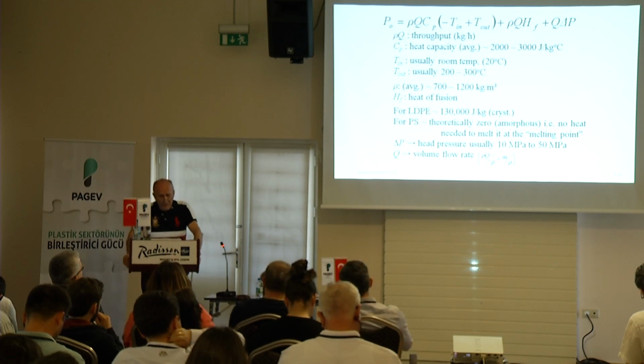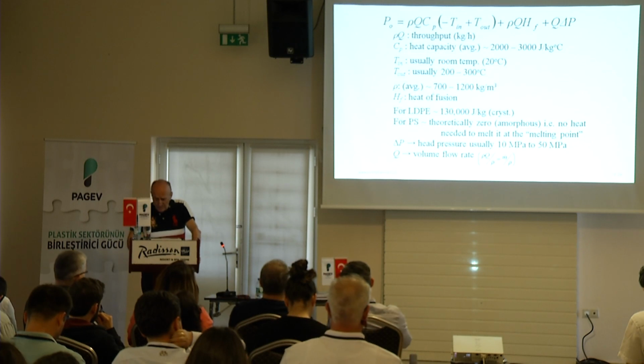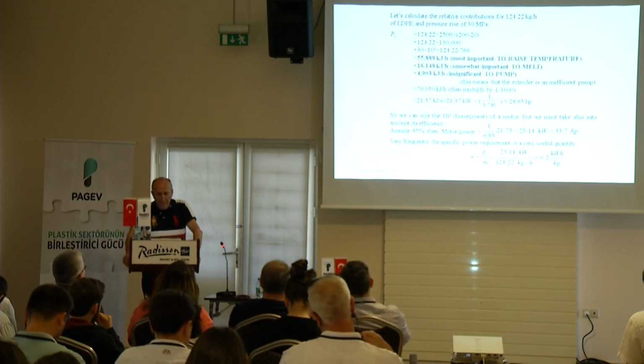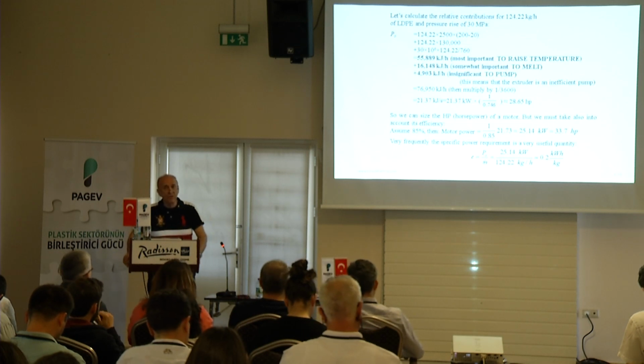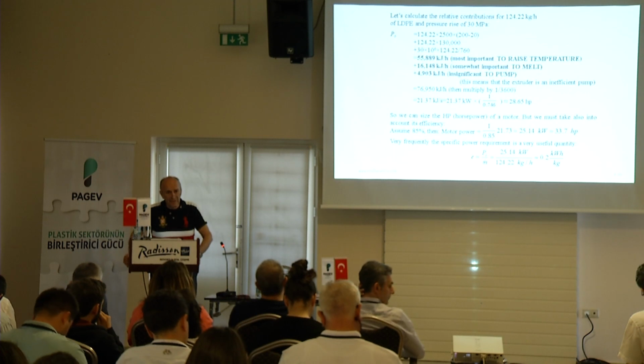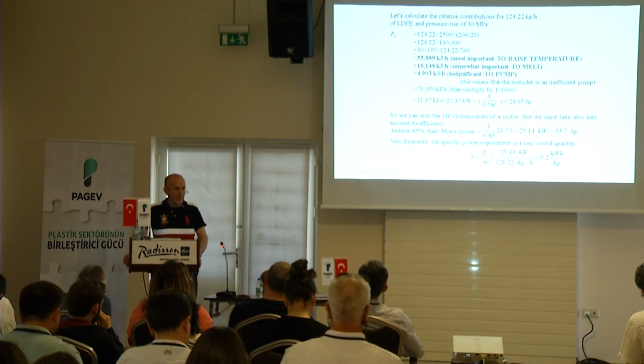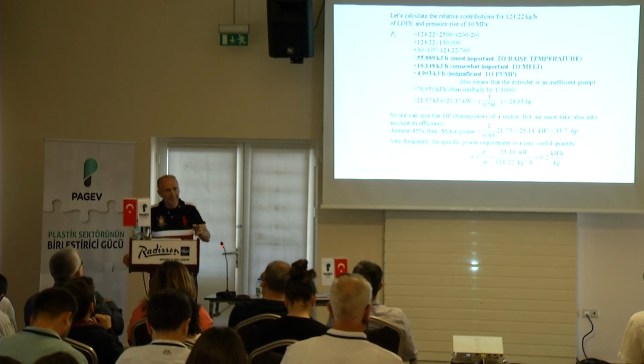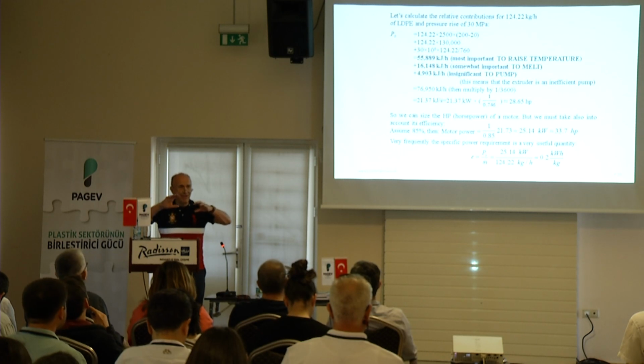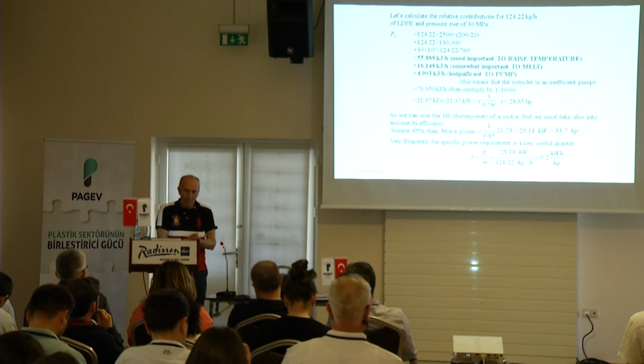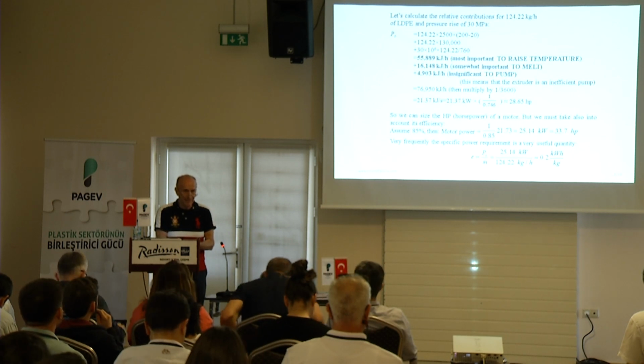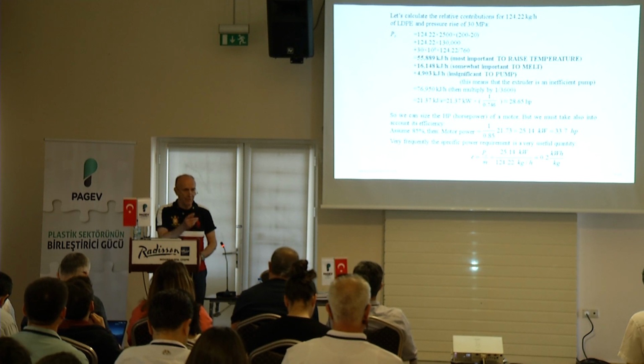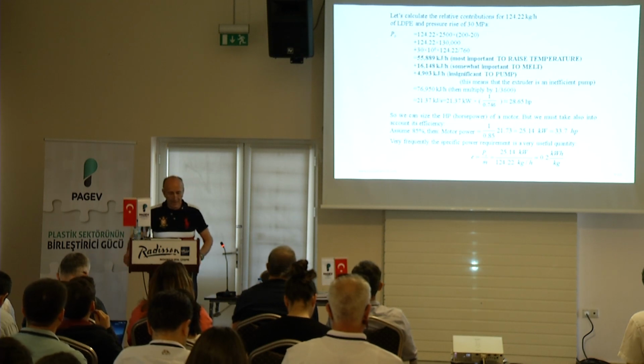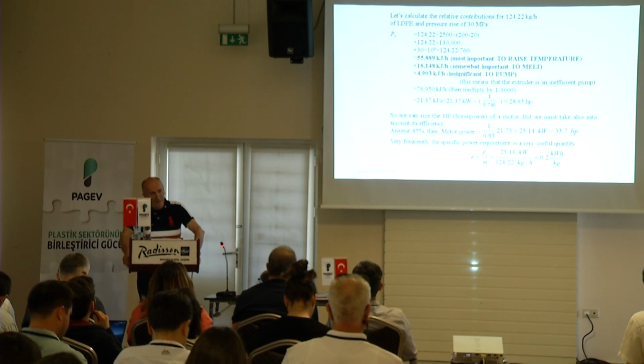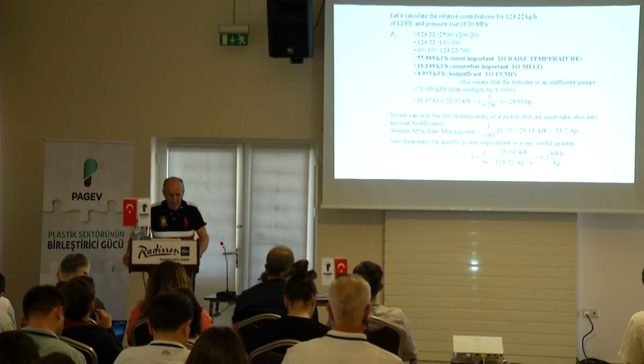Here I do some calculations, and from the calculations, which are explained after that, you will see that most of the energy is inputted by the screw. The rotating screw is what melts the polymer. The heater bands only contribute a small amount. Most of the energy, 80% of the energy, is coming from the rotating screw. The heater bands may contribute perhaps 20%, maybe 25%, no more than that.